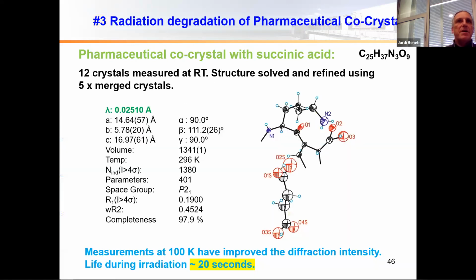What we did is we collected several crystals. So we collected 12 different crystals of this sample and finally merged 5 data sets of the crystals. And we were able to solve the structure and get, let's say, a structure solution which was making sense.